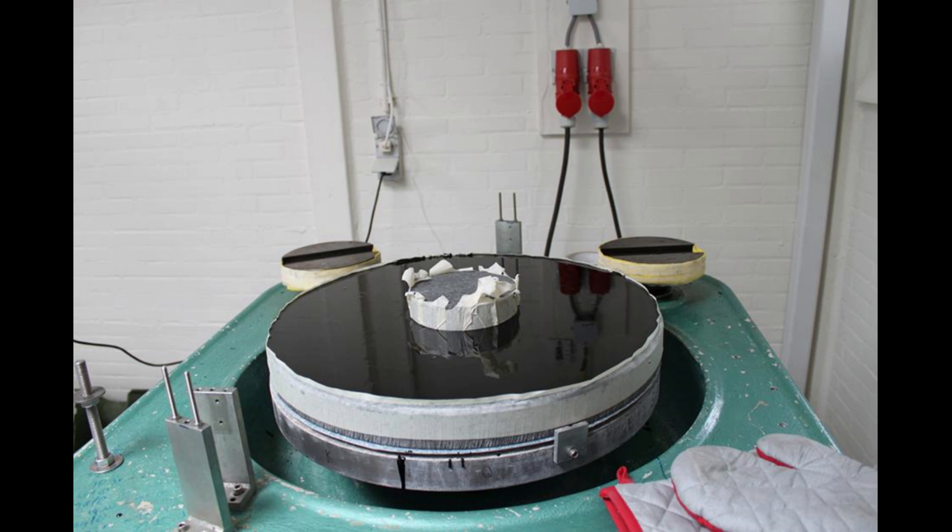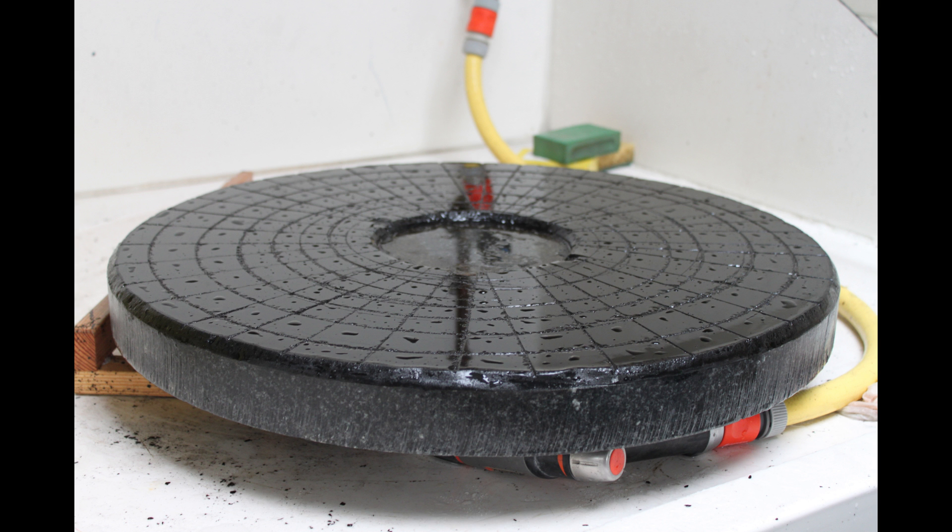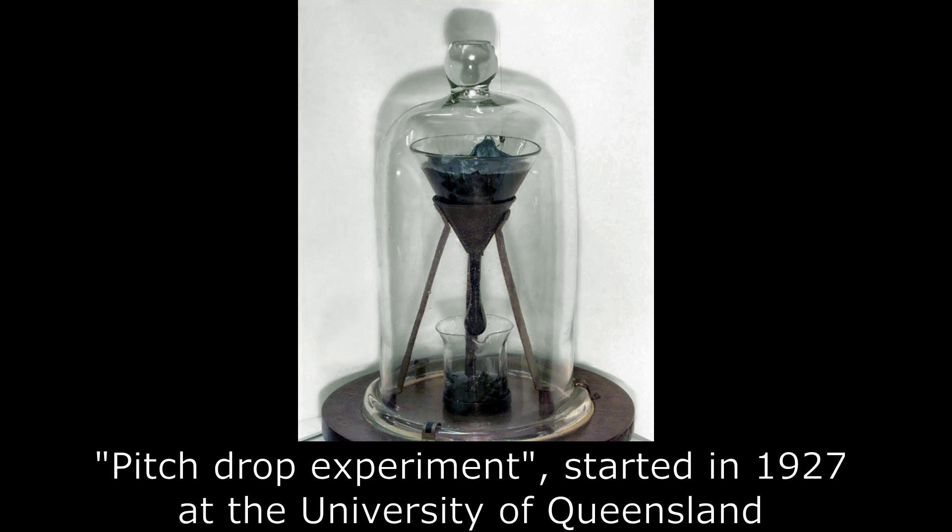For those of you who don't know what optical pitch is, it appears to be a black solid material and it looks a bit like tar. But even though it appears to be a solid material at room temperature, it is actually a so-called Newtonian liquid, although one with a very high viscosity. And this viscosity is strongly dependent on the temperature.